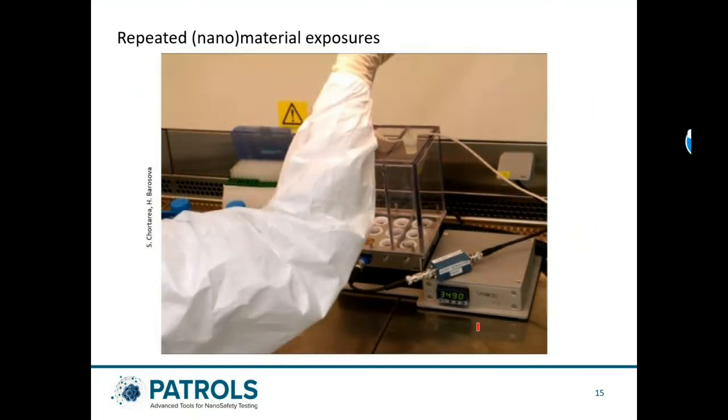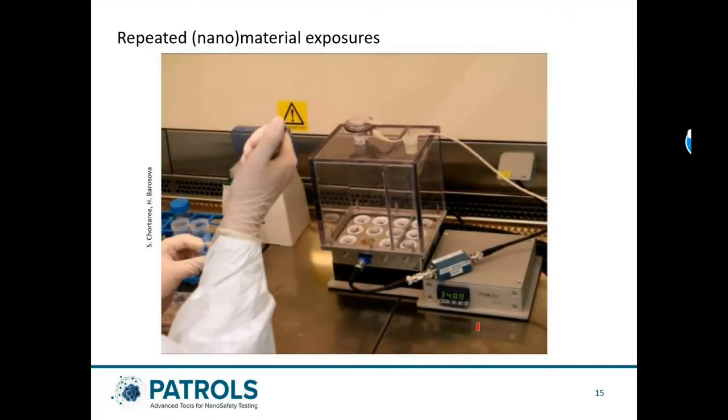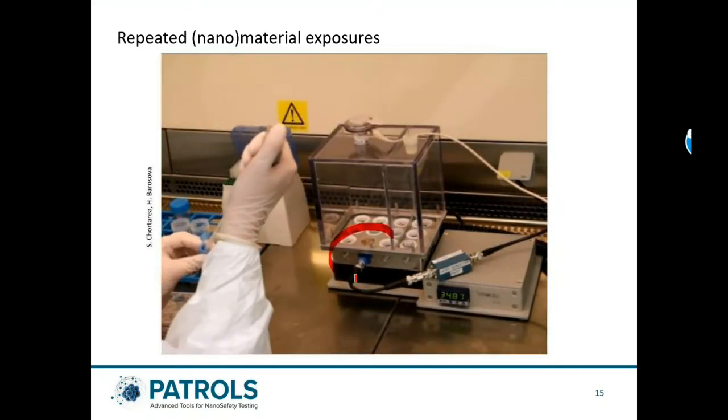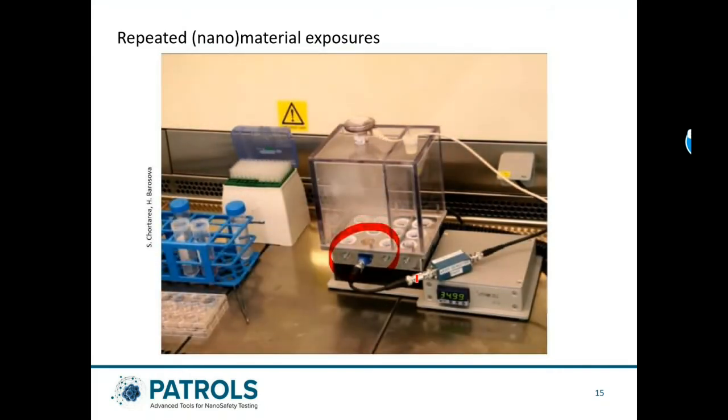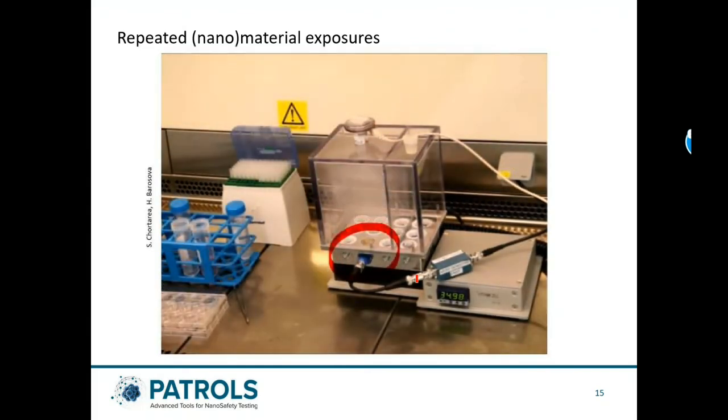So the next step in our lab was to expose these cell cultures to an aerosol, which was done by aerosolization of a well-defined nanomaterial dispersion using the CLOUD system, which is commercially available from VITROCELL. We used the NanoGenoTox protocol to disperse the nanomaterials, and with the integrated quartz microbalance in the system, it's very nice that you can measure the deposition of the nanomaterials online, which is very important information to make predictions about the dose-dependent responses you will get.